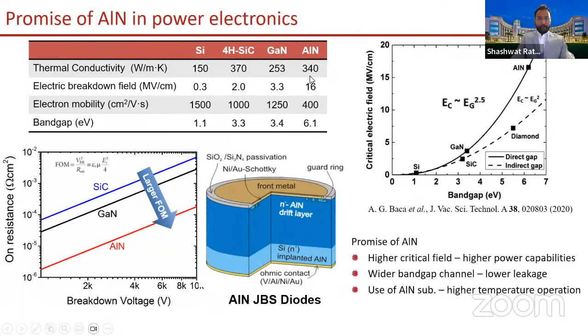So remember, aluminum nitride has a wider band gap, right? So it has 6.1 electron volt, and this helps aluminum nitride to have a 5 times higher critical electric field as compared to GaN, and about 50 times higher critical electric field as compared to silicon. So even though the electron mobility is a tad bit low in aluminum nitride, the figure of merit still translates to a much higher value because of the cube dependence on the critical electric field.